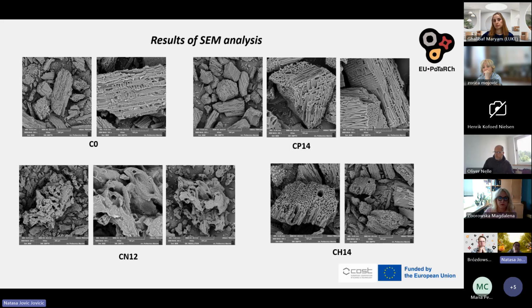SEM images reveal macroscopic surface features and morphological texture. These two images show the control sample results. They are a relatively compact and layered structure, typical for unmodified biochar or charcoal. The surface appears flat with minimal roughness, suggesting limited structural fragmentation.